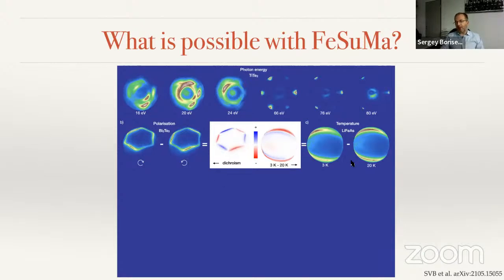The same holds for very precise measurements of the temperature dependence. For instance, if you want to track how your Fermi surface changes as a function of temperature, nowadays it's not a big surprise. In this particular case, we considered the Fermi surfaces at two different temperatures for lithium iron arsenide, and confirmed our previous measurements, which showed that the Fermi surface shrinks as a function of temperature when it crosses the superconducting transition.